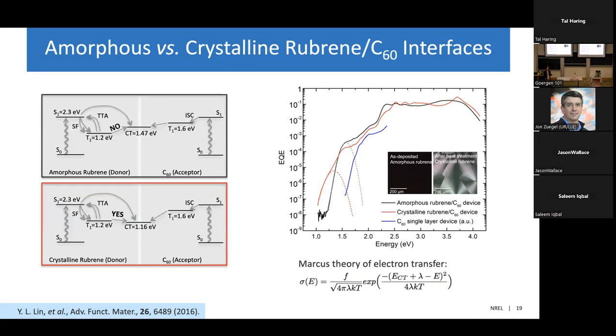And we see something interesting. So for the amorphous rubrene C60 device, the charge transfer state energy that we fit is actually higher in energy than the triplet of rubrene. So even though rubrene is undergoing singlet fission, producing all these triplets, we're not actually able to extract those triplets as charge. On the other hand, for the crystalline rubrene C60 device, the resulting charge transfer state energy is somewhat lower, so we're able to take advantage of the fission process.